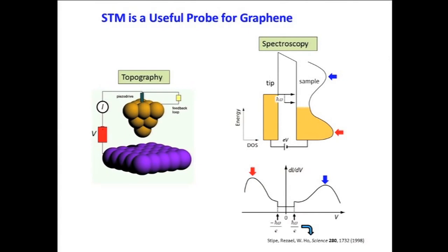Also, the STM allows us to measure inelastic excitations of small structures. And the way we do that is if we put a bias on the STM tip that's big enough so that electrons tunneling from the tip to the surface have enough energy to create an inelastic excitation, then that gives those electrons an additional channel to go from the tip to the surface, an inelastic channel, say by making a phonon, for example, and that then gives us a jump.